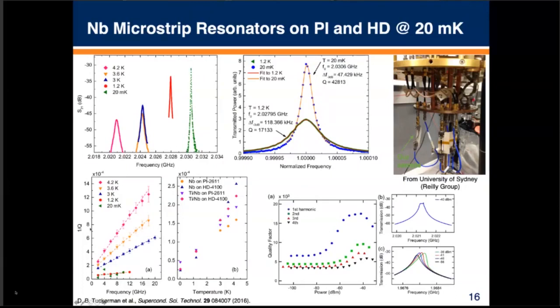One common way to plot this data is 1/Q as a function of frequency, as you see in the bottom left here. And this is essentially the loss of the system. If we're looking at it as a function of temperature, then what's playing into the situation here is that as you continue to reduce that temperature, you have both a small reduction in loss due to the polyimide, but you also have a stronger superconducting state as you go into the lower temperature regime, and so your losses continue to drop in that case.